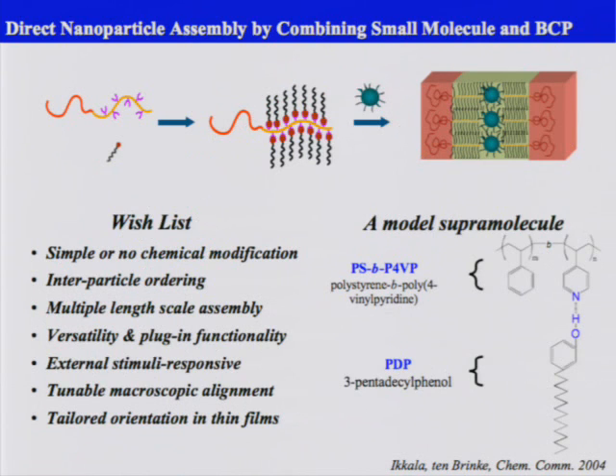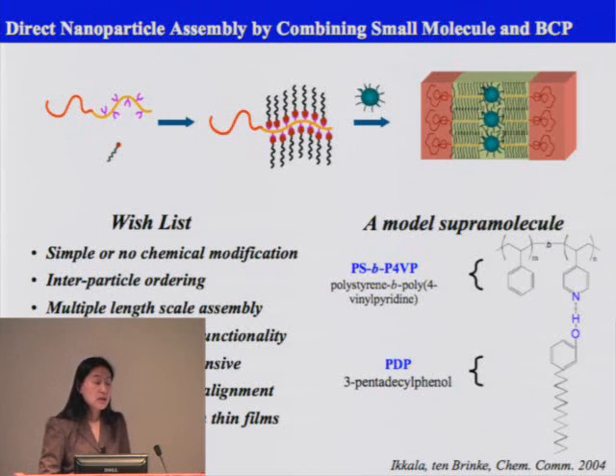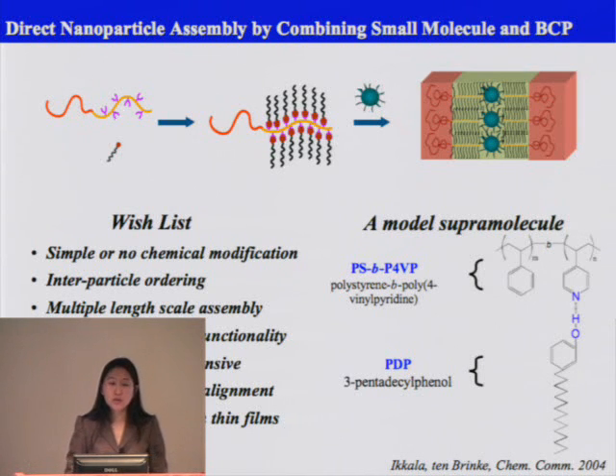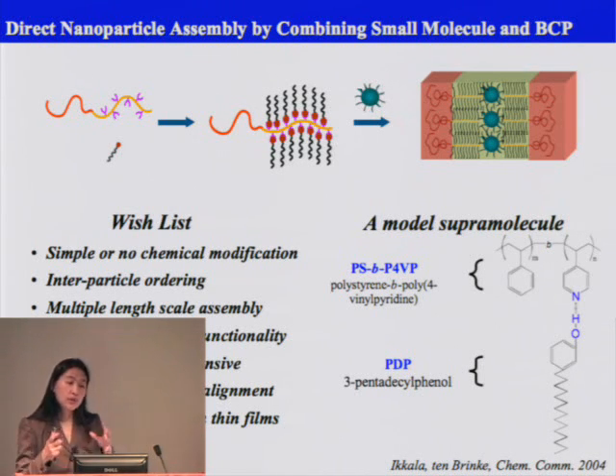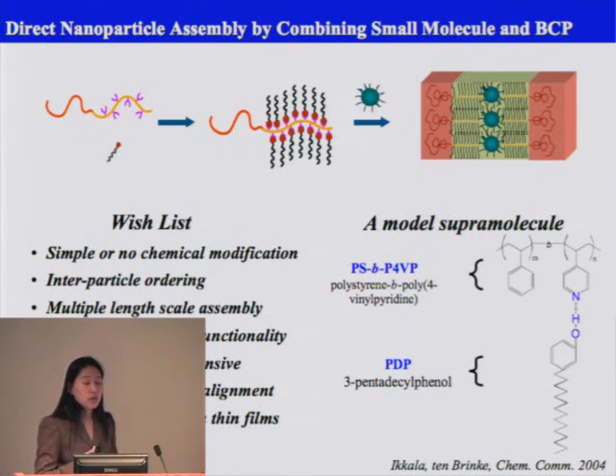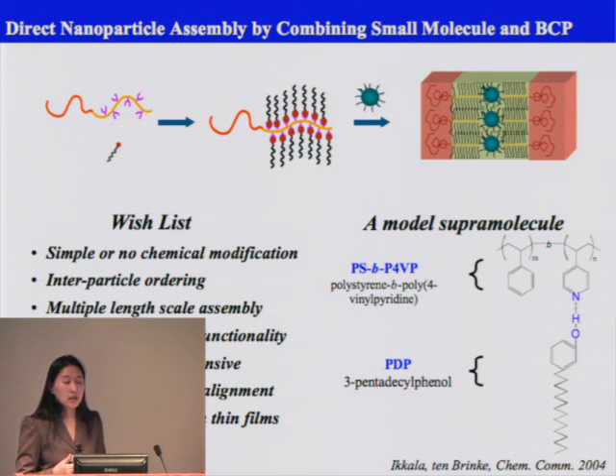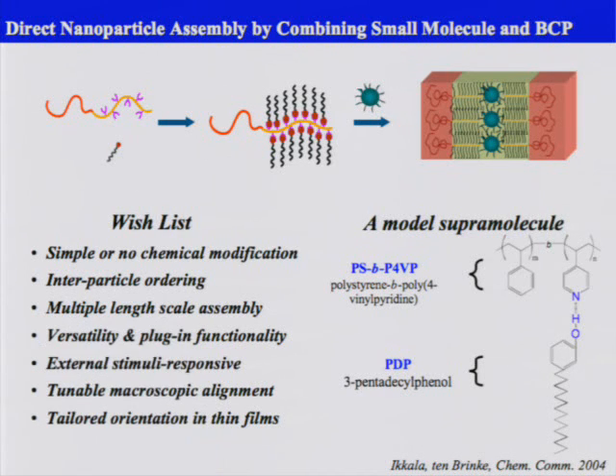So what we are interested in is that we really don't want to modify the particle. We want to use the particle as synthesized. Many of you probably work with using nanoparticles as sensors. Essentially, when you change the ligand on the particle, you can change the optical property of the particle. If you look at lead sulfide, what's on the ligand can easily change it from N-type to P-type. So in order to maintain the built-in functionality, we wanted to just use the particle as is, not to mess around with it.